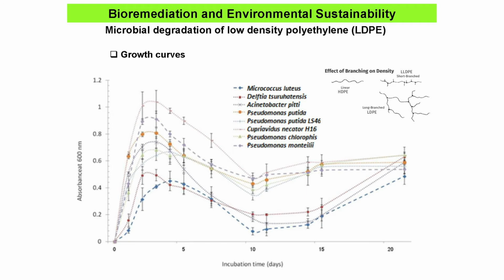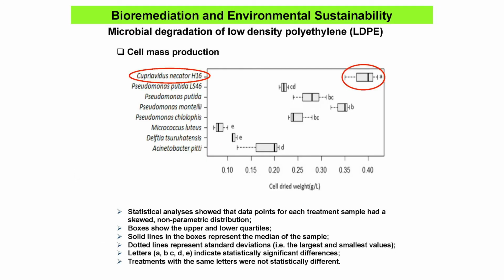And then we did the experiment. And what she found is after pre-culturing those bacteria with hydrocarbons, within 3 days, we got very high growth and very rapid breakdown of the polyethylene. Then they kind of tapered off by day 10, and then we don't know what happens out here. Some of them went down, and then they kind of started going up again. We don't know exactly what's going on. But this very, very rapid degradation was very evident. We found that if we look at cell mass production, we had this Cupriavidus necator, which synthesizes these short-chain PHAs, had the highest biomass production compared to the others.